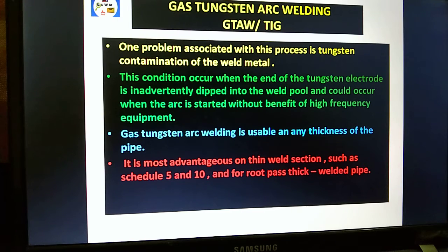One problem associated with this process is tungsten contamination of the weld metal. This condition occurs when the end of the tungsten electrode is inadvertently dipped into the weld pool, and could occur when the arc is started without the benefit of high frequency equipment. Gas tungsten arc welding is suitable at any thickness of pipe. It is most advantageous on thin weld sections such as Schedule 5 and 10, and for the root pass of thick walled pipe.